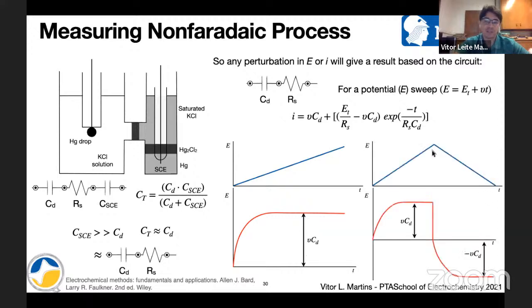And then we can change the direction of the sweep. So now we are decreasing the potential over time, but we are controlling it again. And then we have this kind of response, right? So first it increases, and then we invert it, and then we have the negative current, and then we are getting again back to the current that is related with the product of the scan rate with capacitance. Remember that here is wrong, so it's current. We are measuring current and applying a potential.